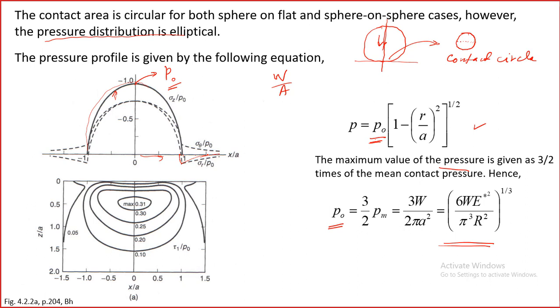So whenever we are keeping a ball on a surface, like in a ball bearing, of course there is a stress here at the contact, but even beyond the contact also there is some stress, and this stress is tensile in nature. So that's the reason why we see that fatigue happens in this case, because of the tensile stress which goes beyond the contact point.